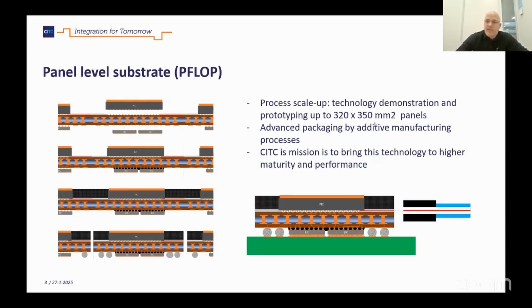At the core of our package concept, we start with a glass panel, and on one side of the glass panel we create an electrical redistribution layer by additive manufacturing, which allows us to integrate the electronics on one side of the package. Then, by high aspect ratio vertical interconnects, we create the electrical path to the photonics, and on the photonics side we use the polymer waveguide technology of Vario Optics to make an optical redistribution layer on the opposite side of that panel. Our mission is to bring these technologies to a certain technology readiness level so that they can be adopted by the industry.